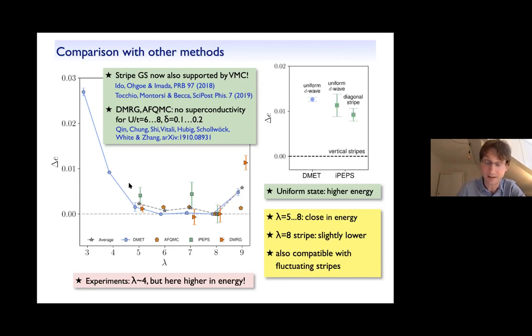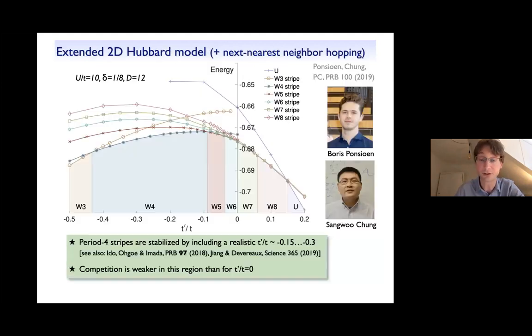And to get more insights into this, what we did was to look at an extended 2D Hubbard model, including a next nearest neighbor hopping term, which is known to be present in more accurate effective models of the cuprates. So I show you here data which was obtained by Boris Ponsioen and Sangwoo Chung from our group. That's the phase diagram as a function of t' over t, for U over t equals 10, 1/8 doping, and for a fixed bond dimension of 12. And what you can nicely see is that as we increase the strength of the negative t', there's a shift from longer stripe periods to shorter stripe periods, with a large extended region of stable period 4 stripes. And this also includes values which have been predicted as realistic values for the cuprates.